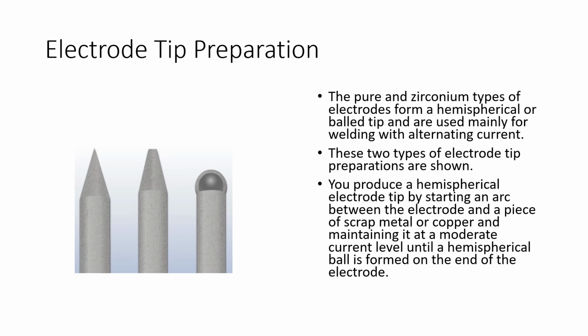The pure and the zirconium types of electrodes are going to form a hemispherical or a balled tip. We usually use this when we're welding with alternating current, and this would be welding on aluminum. Most of this I cut out of a military manual, so it guides us through it, but I didn't give the full, down and dirty on this. I'm just giving you a skim of it. To produce a hemispherical electrode tip, you strike an arc on a piece of copper or scrap metal, and you wait until the tip heats up, and then it's going to ball up like that. It's going to form on the end of the electrode.